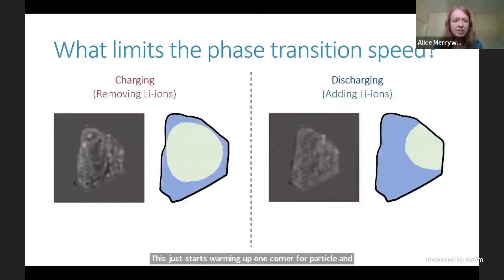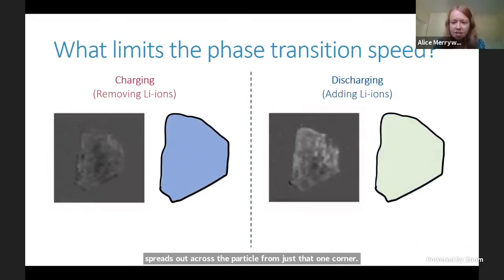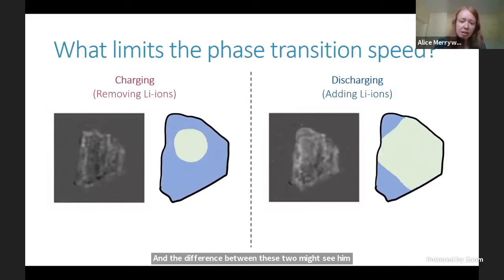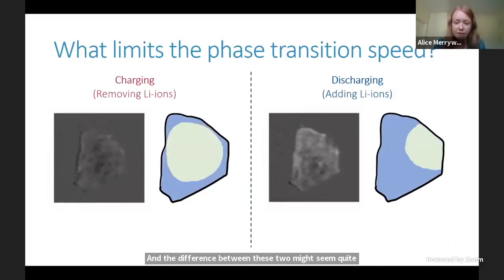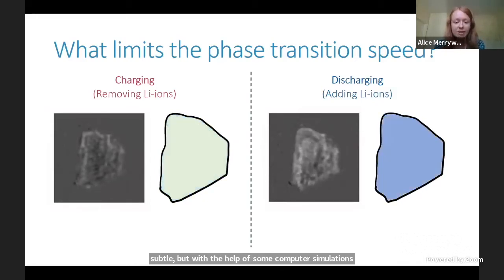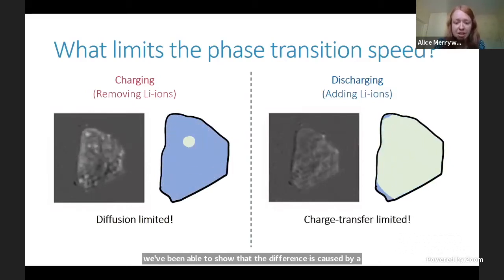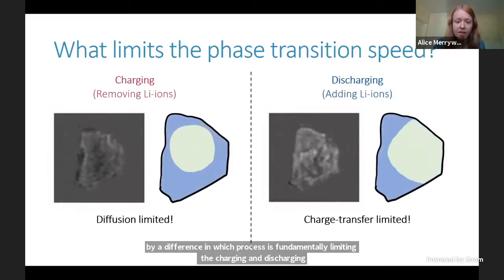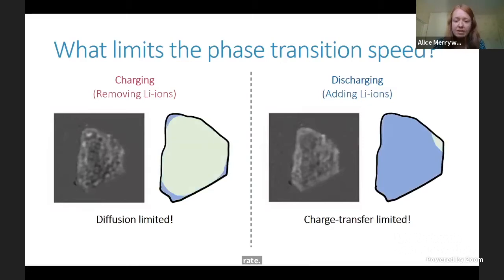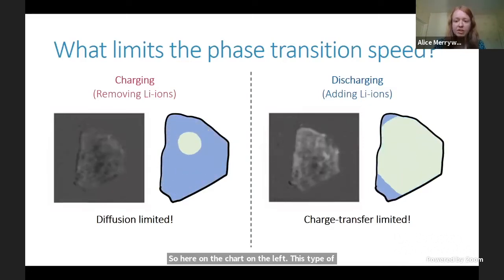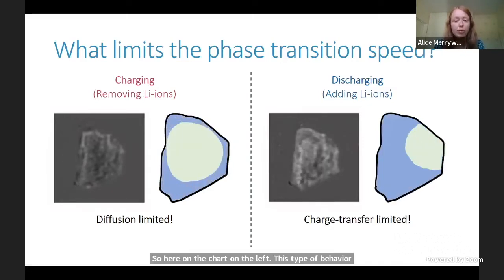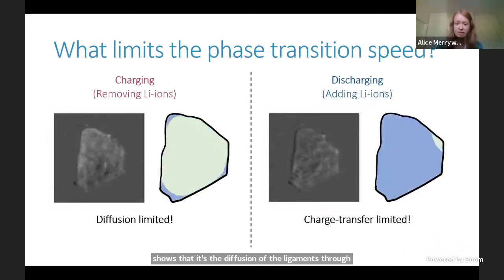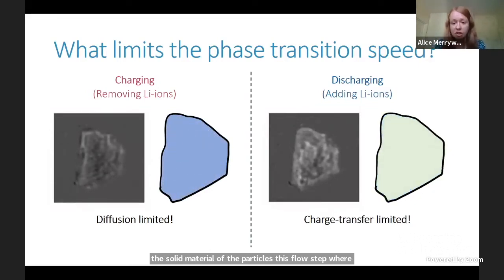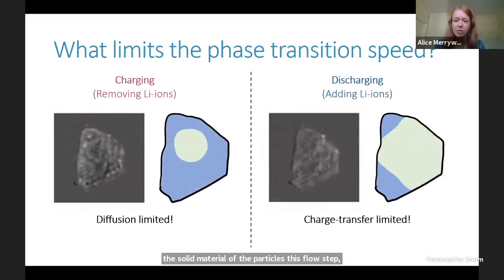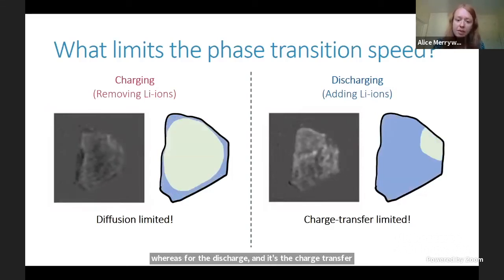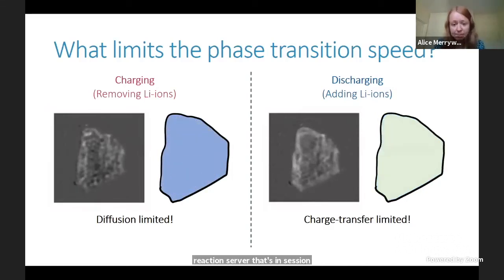And the difference between these two might seem quite subtle, but with the help of some computer simulations, we've been able to show that this difference is caused by a difference in which process is fundamentally limiting the charging and the discharging rate. So here on the charge on the left, this type of behavior shows that it's the diffusion of the lithium ions through the solid material of the particle that's the slowest step. Whereas for the discharge, it's the charge transfer reaction. So remember, that's the insertion of ions at the surface of the particle, which is the rate limiting step.